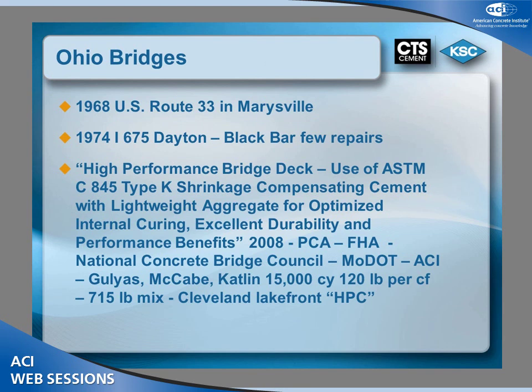And in 1974 on I-675 in Dayton, all the bridge structures used black bar. They did not use green bar in this. And those structures today, we went and looked at those, and there is no spalling and no corrosion problems in regards to those decks, and we couldn't find cracks in these decks. Now, there are some areas that have actually had an epoxy overlay, but that's been for some other reasons, but these decks are in pristine condition.